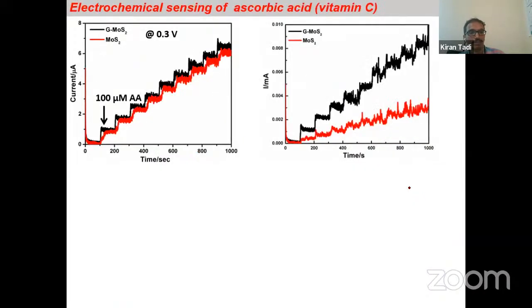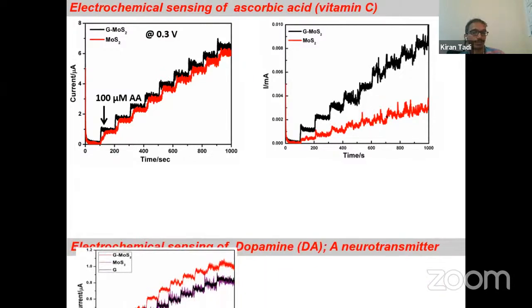Using this, we made stable sensors. In the case of graphene-MoS2, you can see stable sensing of ascorbic acid, even the first trial and third trial are the same. But in the case of molybdenum sulfide alone, the sensitivity signal has reduced.